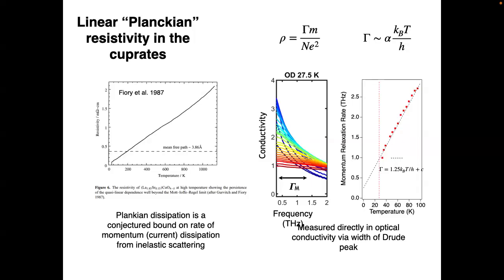Yeah, so you have to fit it to some functional form. And so when we're fitting this, we're assuming it's a Lorentzian, which is a good approximation at low frequencies. And when we're fitting, it's not just the real part, because as with any experiment, you're kind of spectrally limited by the technique. But we also fit to the imaginary part at the same time to help us constrain that. So it's this fitting of the real and imaginary parts of this response at the same time which allows us to do this with high fidelity. But it comes with an assumption. That's right. So we'll talk more about that.